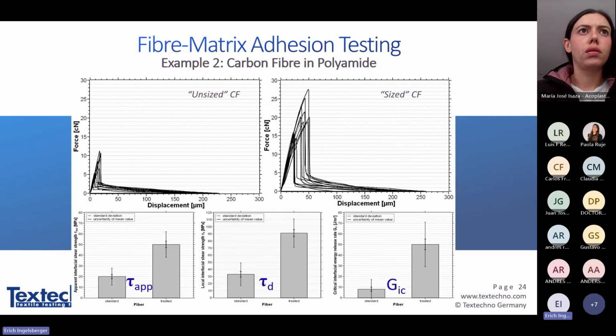The next example is a carbon fiber embedded in polyamide. The fiber here is unsized, there is no sizing on the surface. Here are some special contact-improving sizings on the fiber. Here you can see the unsized and the sized fiber, that's the apparent interfacial shear strength only by force. You can already see this by looking at the force displacement curves. This is the local interfacial shear strength, where the crack is initiated, and the energy release rate.